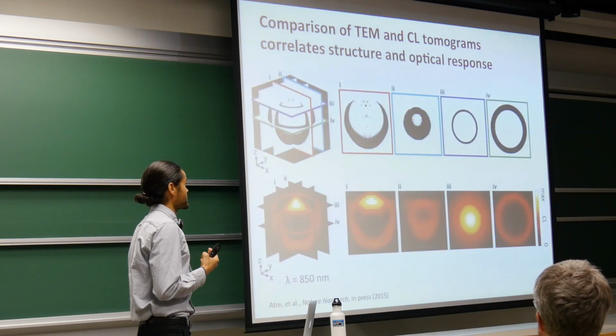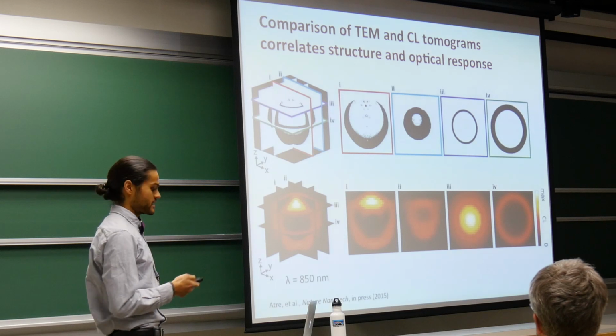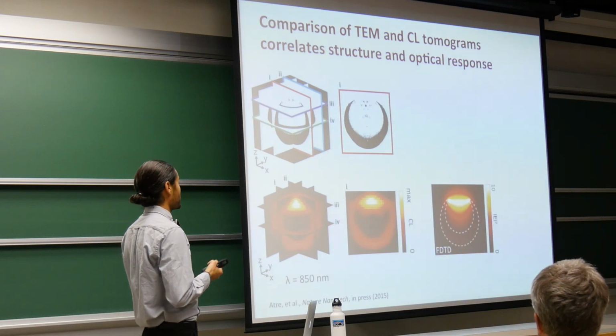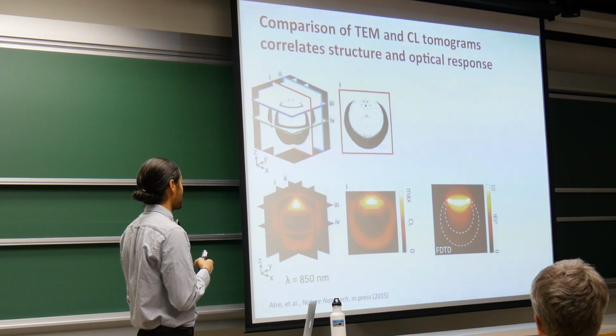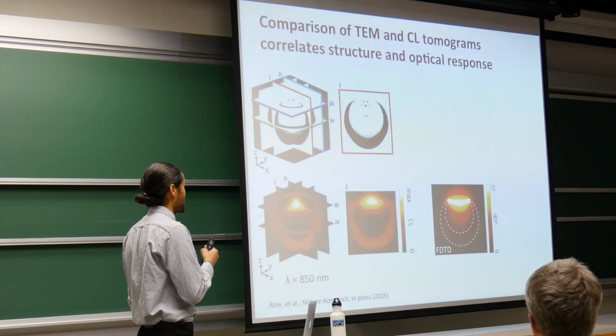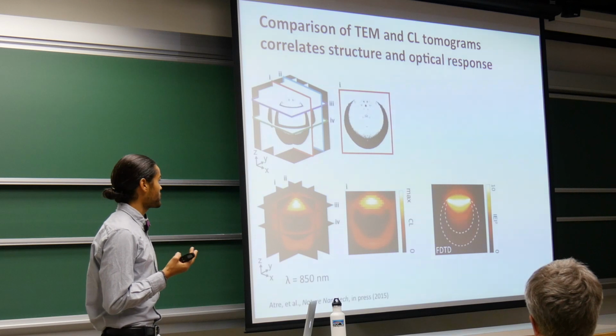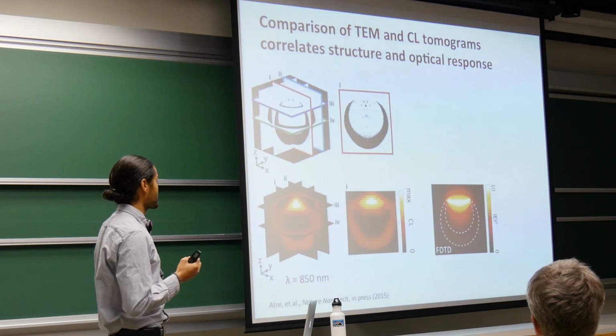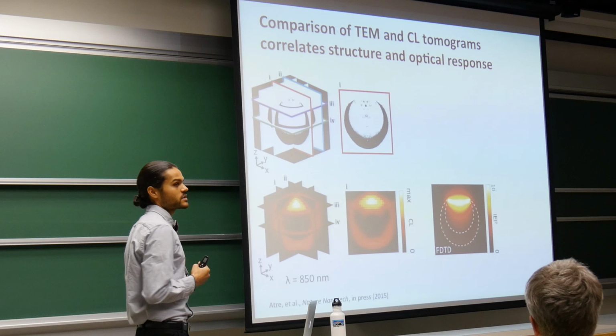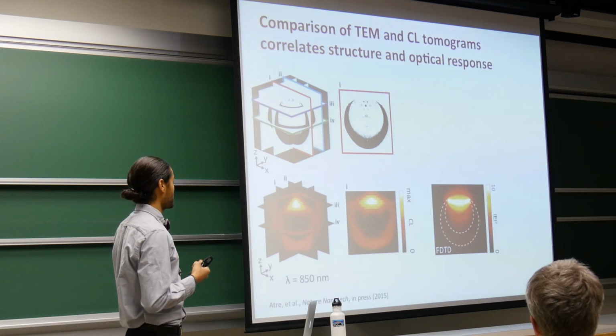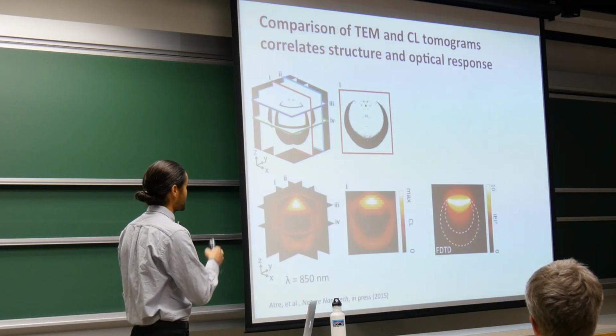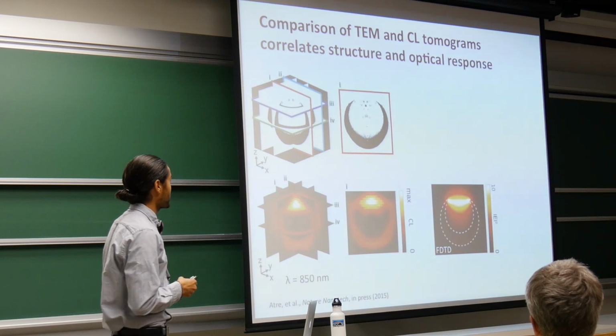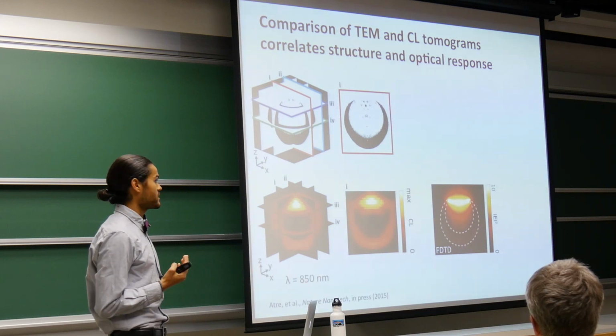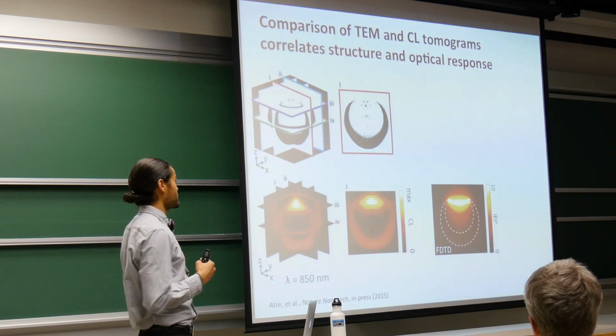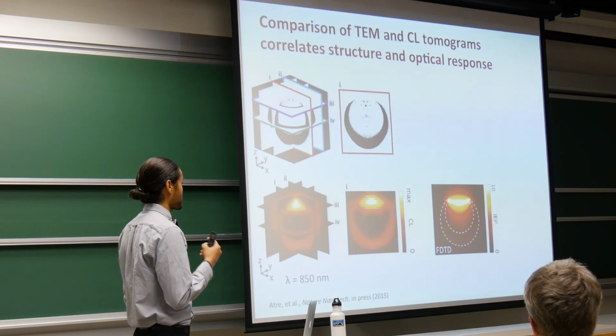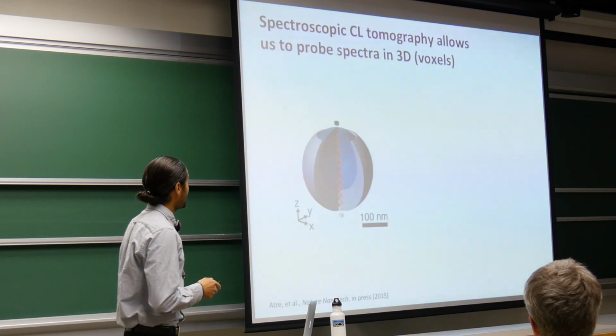Looked at in a static view, we can chop up our tomogram into slices. And what's most interesting here is that when we compare the experimental photoluminescence slice from the tomogram on the left with our original field profile calculated using a finite difference time domain method, we can see the great correspondence between the experimental and the theoretical predictions. Here I'll just note that the signal that looks like it's coming from the shell of the crescent is actually, like I mentioned, the material luminescence, which isn't taken into account for this particular simulation. That's why they do look slightly different.